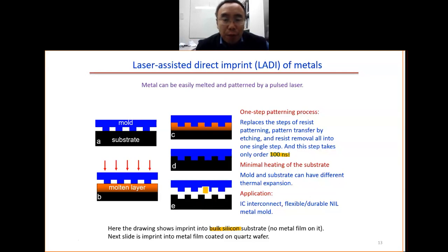This paper is published in Nature in 2002. You may wonder what's the importance of this. Normally, when we make the structure in the silicon, we need to do the lithography. We need to pattern the resist by lithography. We do the pattern transfer. Then we remove the resist. We need 3 steps to do the pattern transfer to the silicon. But here, we only do 1 step. Just shine the laser, you pattern the silicon right away.